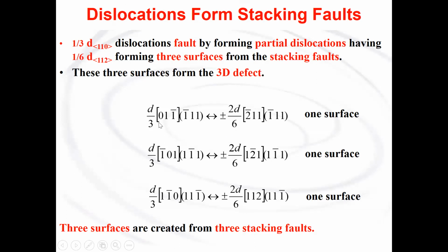So the a/3 01̄1 can form 2 partial dislocations having a/6 2̄11, which will form 1 surface. And then likewise, the other 2 dislocations can form the 1̄21 and 11̄2 type of dislocation. So we can generate 3 surfaces from these 3 stacking faults.